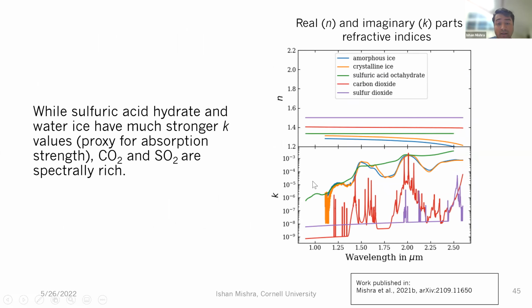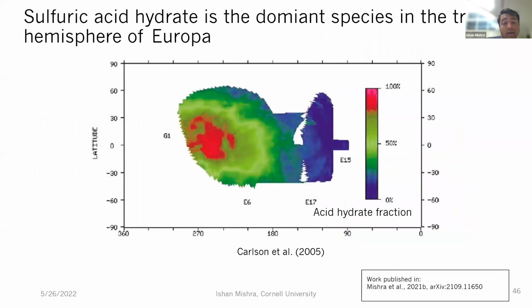Yeah, so here I'm just showing the absorption coefficient, or proxy for absorption coefficient, which is the imaginary part of refractive indices for all our candidates. And the reason I'm including this is just to highlight that carbon dioxide and sulfur dioxide do have a lot of sharp features in this wavelength region. We don't really directly see them in the Galileo NIMS data because the bulk components are just orders of magnitude stronger, like the water ice and sulfuric acid hydrate here. But we still wanted to include them in our modeling analysis, because the point is to have all your candidates that you think are present and systematically find the best subset that works.